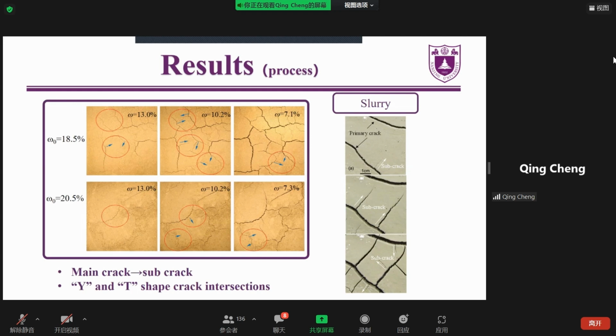When the primary cracks initiate, the internal tensile stress perpendicular to the existing primary cracks is released, and the new maximum tensile stress is parallel to the existing primary crack. Thus, the subcracks grow at the local maximum tensile stress, which is perpendicular to the primary cracks.